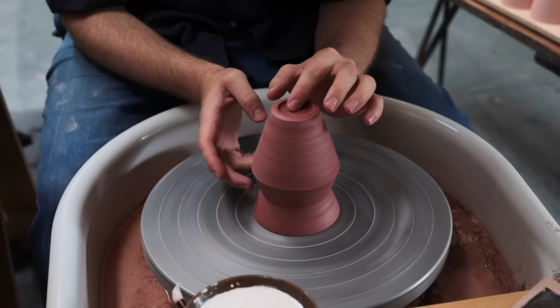about, a link to which you can see on screen now, and I'll include another link in the description below. With the pot centered, wax is brushed over the entire base, creating a barrier that the water in the glaze won't be able to be pulled through, and therefore the raw materials that are mixed into the water cannot stick onto this waxed surface. This extra dab at the end is just to make sure my maker's mark is fully covered, as trying to dig the glaze out of that small indentation can be a pain.